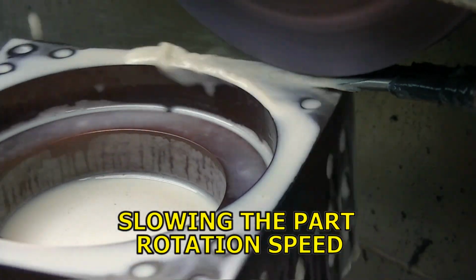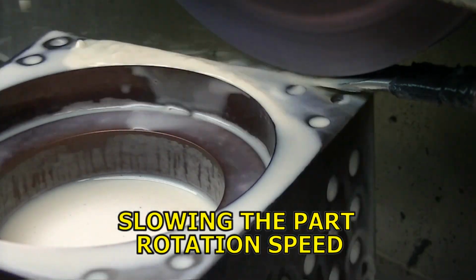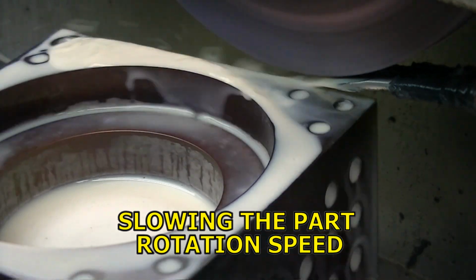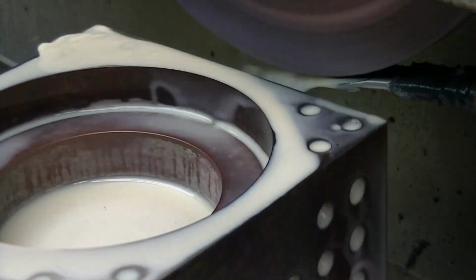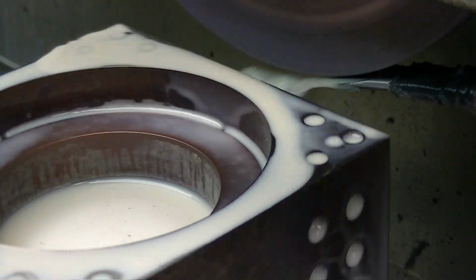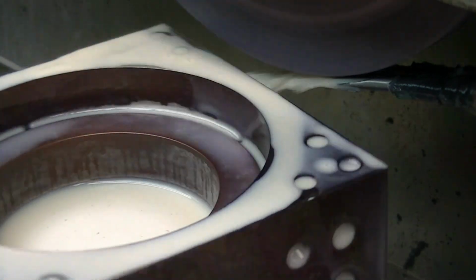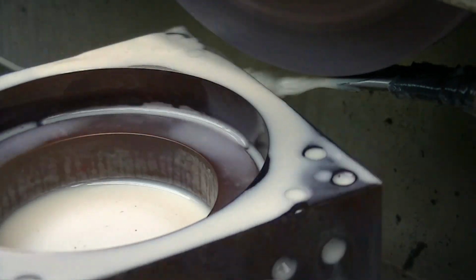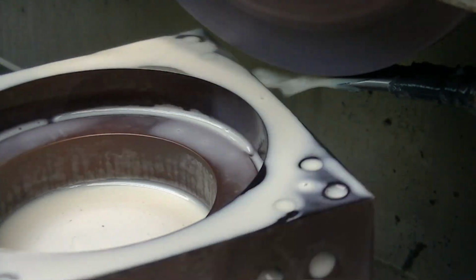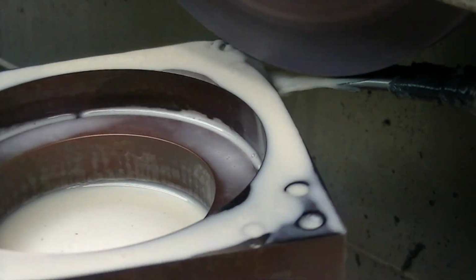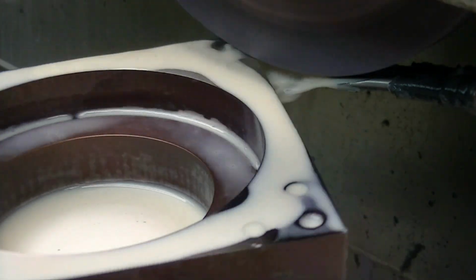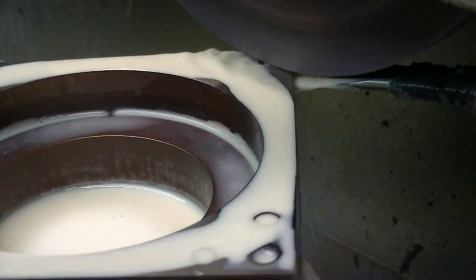Slowing the traverse makes those scallops occur much closer together. And then my traverse rate across the part is also very, very slow. It's half an inch a minute. And I can still hear it grinding, so this was a 30 millionths cut, but you don't know whether it's actually 30 millionths or not because the system still sprung some.